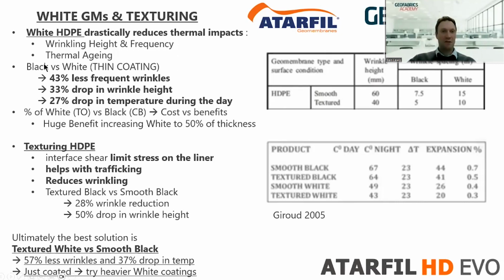And there's some stats here as well. So these stats here relate to a thin white coating, by the way. So we could actually increase the thickness now with these HDPE to maybe 50% of the membrane, and there's even better improvements with these properties. But just looking at thin coating, we're seeing 43% less frequent wrinkles, 33% drop in wrinkle height, and a 27% drop in temperature during the day. So significant benefits, and I've touched on what they are. So now we're actually promoting increasing that thickness to maybe 50% of the material, because you get even better temperature drops and better properties with wrinkling and frequency of wrinkling.